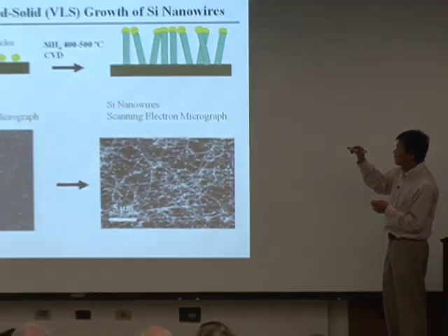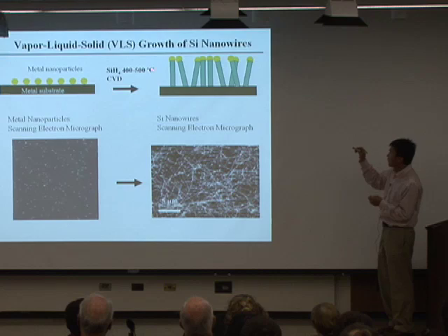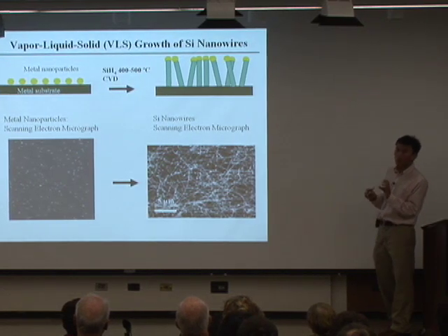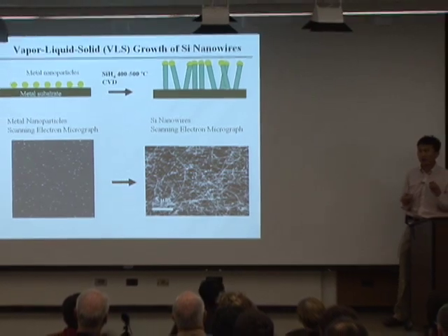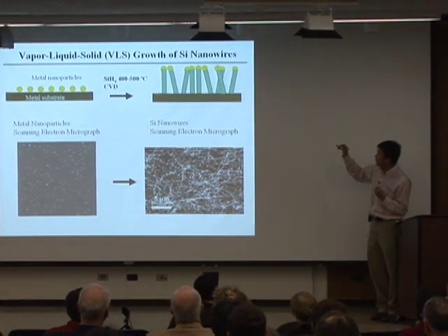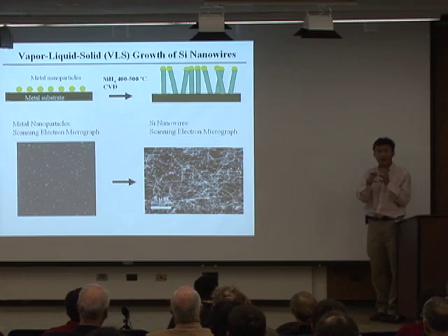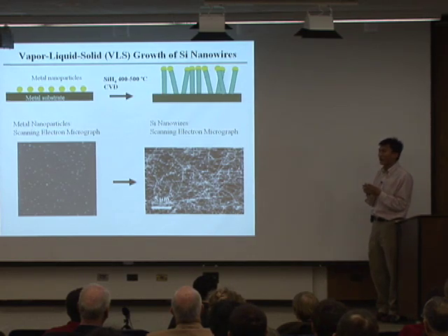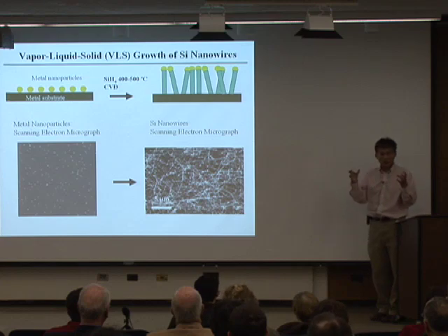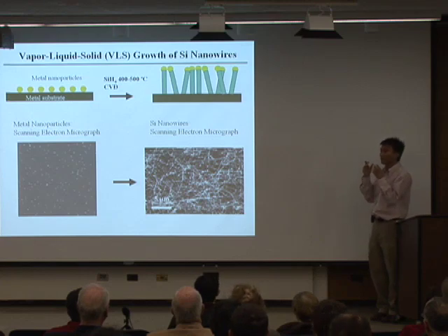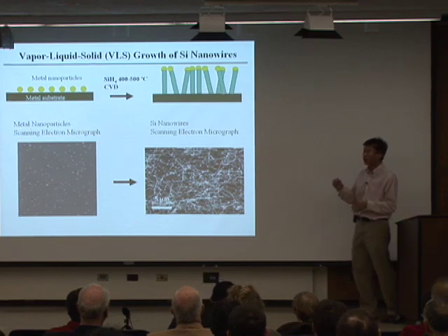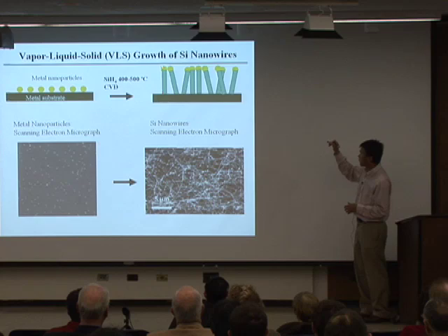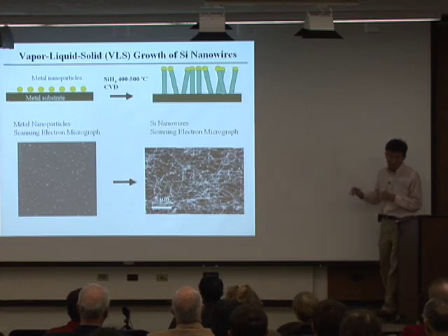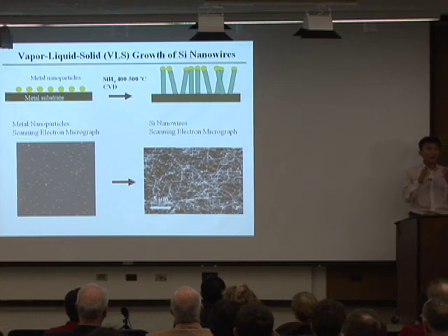So we use the catalytic method, using metallic particles under the CVD growth condition, and grow this nanowire directly out of the metallic substrate. You really gain the advantage. The bonding right here is chemical bonding, very, very strong. So you don't need to use any binder to hold this nanowire together. You don't need to use conducting carbon to help the conduction, because electron transport is so efficient within the nanowires. These are the nanowires you get, typically about 100 nanometer diameter also.